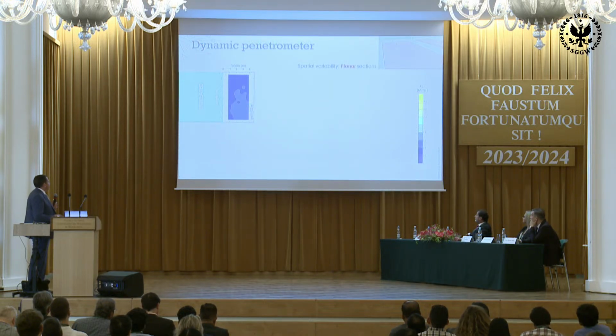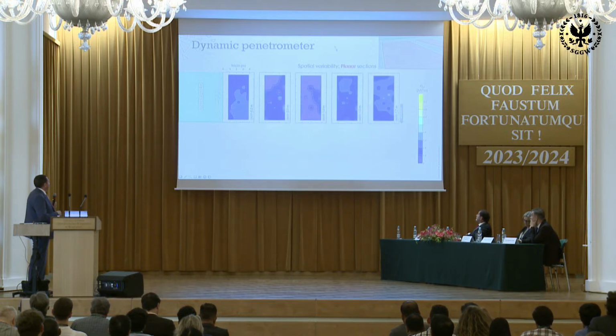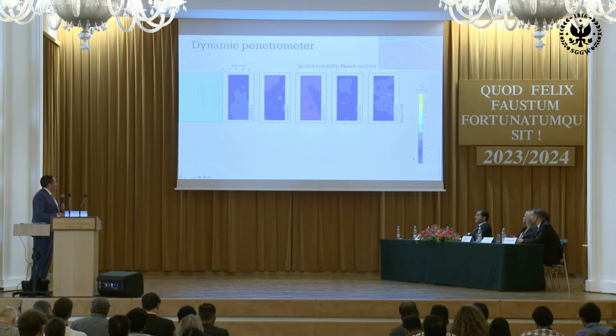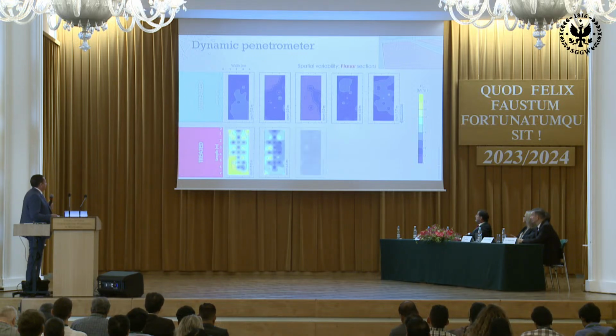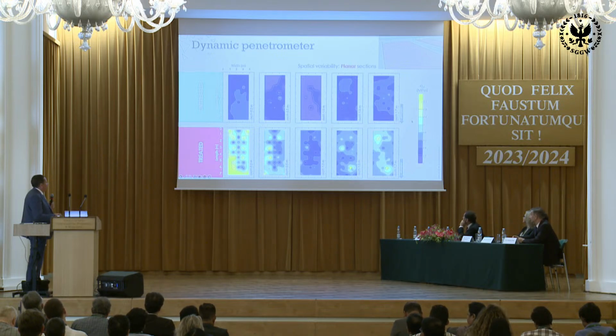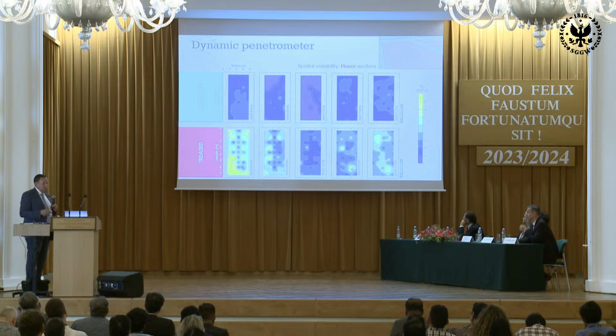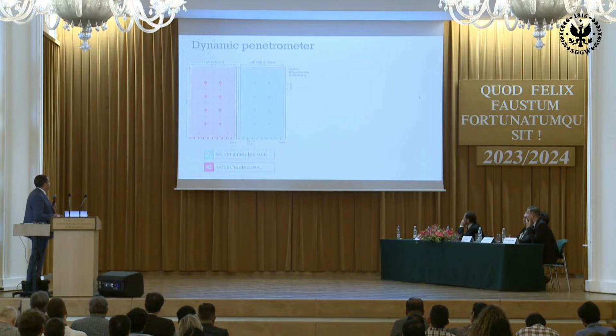So this is first an untreated part, so we can analyze it with the dynamic penetrometer. This is at different depths, and basically we see that we have small values of resistance in the material. And now I show you the case of a treated material where we inject, and basically you see that we are going towards a yellow part, so it means that we are increasing the strength of the material. This is a global view, but let us look at it in more detail.